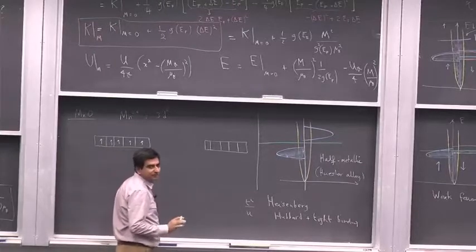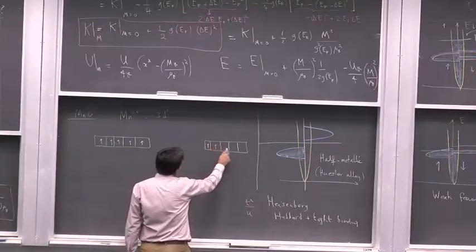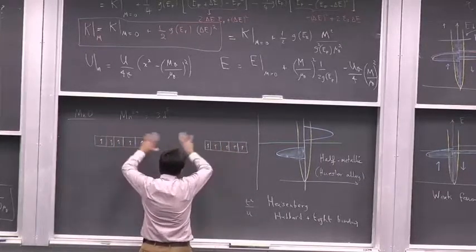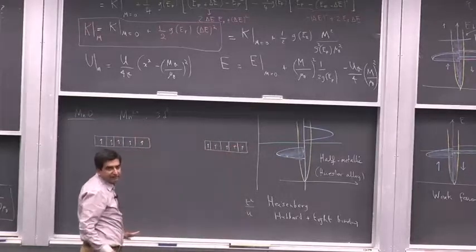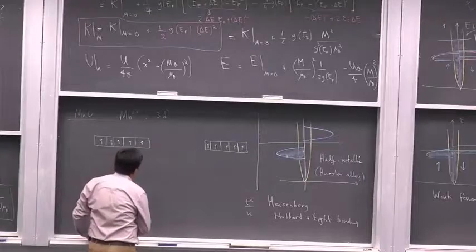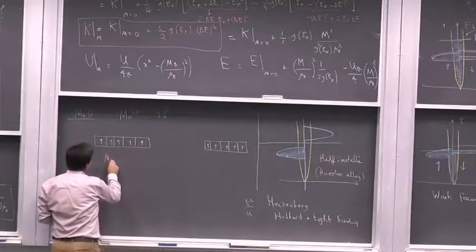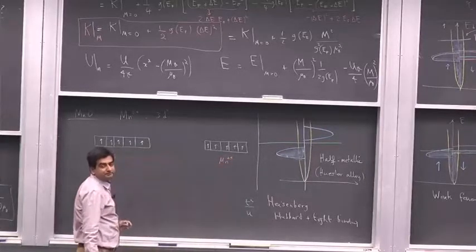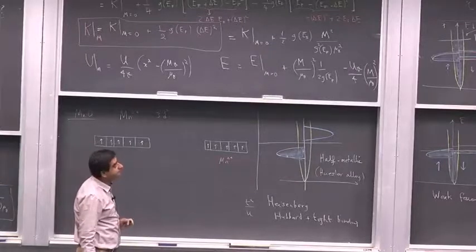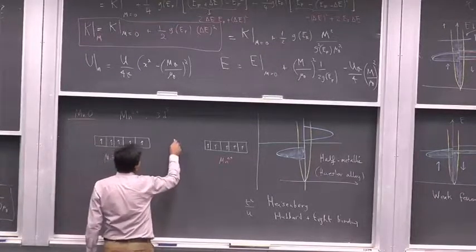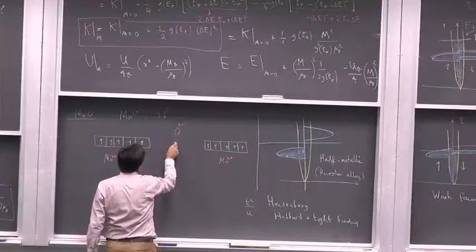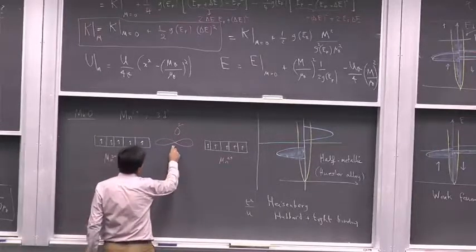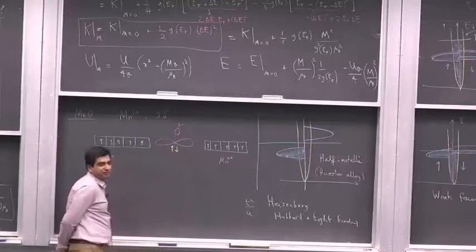Now let's suppose we have a second manganese atom in which all of the electrons are parallel, and in these two separate manganese atoms, both of them are parallel. Let's suppose this is the case. In between we have an oxygen anion. So this is a manganese ion. It's an ionic crystal. And you have an oxygen anion in between, and you have the 2 electrons in a p orbital, and they must be anti-aligned because of the Pauli exclusion principle.